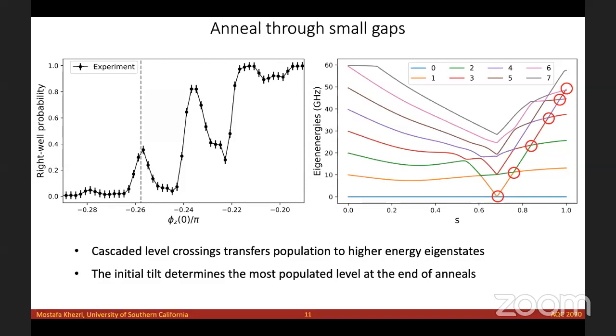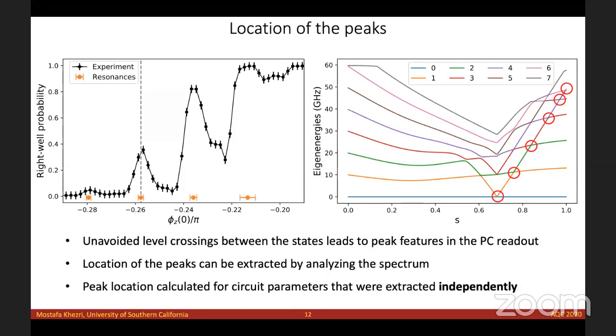So just by this, we can use the previously fitted model that I showed you, and just extract where we expect the location of these peaks to be, which we're showing with these orange circles. You can see that just using those independently measured circuit parameters, using the asymmetry measurement and the spectroscopy, we can just predict these features which are due to the higher eigenstates of the circuit.